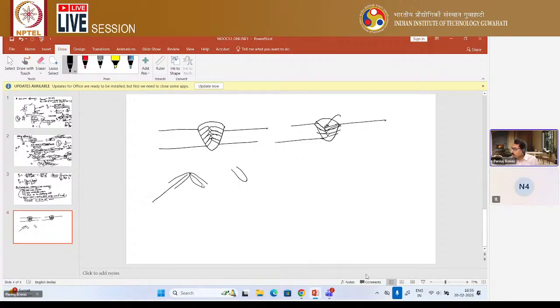Here you see, the angle is less than 90 degrees. In this case, if it is the downward direction, then the angle of the grain here is more than 90 degrees. This is the angle between the columnar grains. If the grain orientation is in the downward direction, your angle is greater than 90 degrees. If the grain orientation is in the upward direction, where the angle between the two side grains is less than 90 degrees, then your chance of solidification cracking is less. It helps to prevent solidification cracking if your grain orientation is upward. This you should keep in mind.